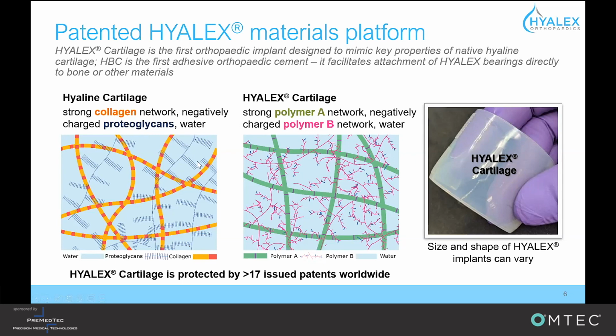Similarly, HYALEX cartilage, shown on the right side, is also composed of a strong polymer network, shown in green and labeled as polymer A in the right diagram. And this is combined with a second negatively charged polymer, polymer B here, shown in pink, that draws in the water. This water is also able to move in and out of the material in response to loading in a similar manner to native cartilage.